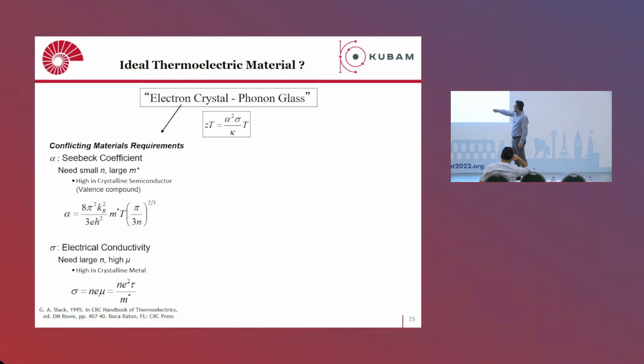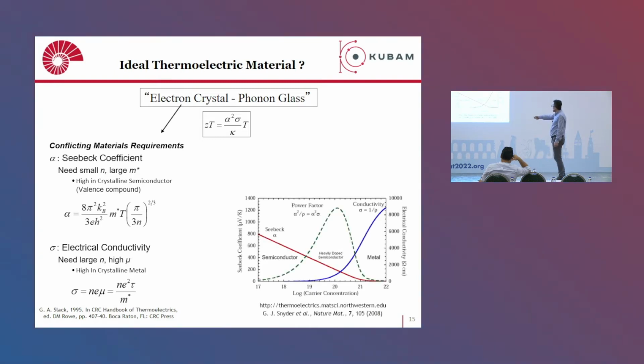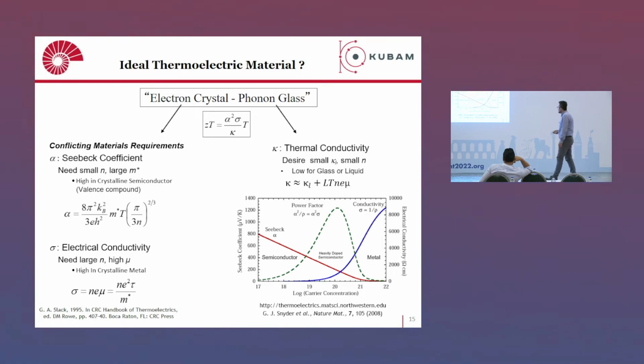So on the other hand, for the semiconductors, you can see that they generally have low carrier concentration and large effective mass. So here you can see that the power factor, which is the Seebeck coefficient squared times the electrical conductivity, is maximized for basically the carrier concentrations within this window. So let's say 10 to the 19 to 10 to the 21 per centimeter cube of carriers. And this is valid for the heavily doped semiconductors. So you should tune the carrier concentration in a sense to tune the electronic properties.